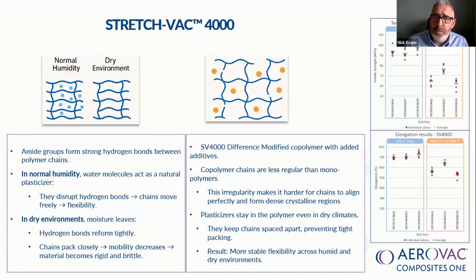So what the Aerovac team did is develop a specially developed production formulation, where we modified the polymers to make the chains more irregular. The moisture within the chains and within the plasticizer then keeps the film softer and makes it easier to work with. That's also given us higher mechanical properties, as you can see there. We see high tensile strength values at room temperature of nearly 100 MPa, and really high elongation values of nearly 700%.